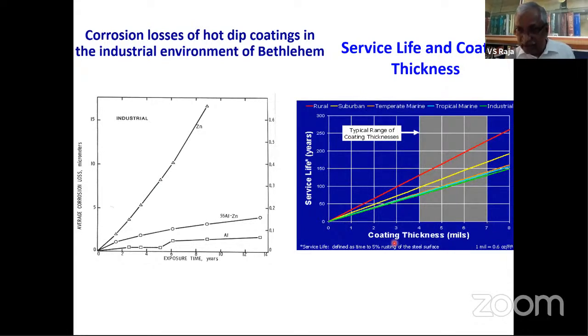Can we reduce the thickness? Can we improve the properties? Can we have better properties? Because we have no resources of zinc, and zinc is increasing the cost and so on. So can we have thin coatings and have excellent corrosion resistance? And that's where you see here. The example in this left-hand side diagram is average corrosion loss versus exposure time. You see the loss in corrosion for zinc, and you have zinc aluminum, and you have aluminum here.